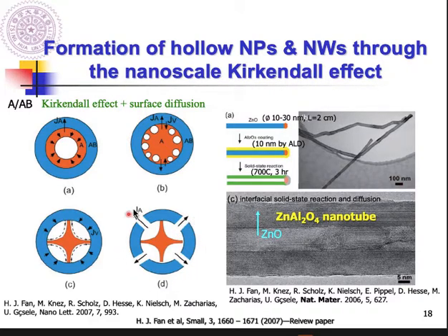Then you can fabricate this kind of nanoparticle with this special geometry. And this channel or tunnel can also allow you to load some drugs or add some special compound into this nano particle, serving as a drug carrier or some material carrier for different applications. And this is the case of manipulating different hollow nanoparticles by the Kirkendall effect.